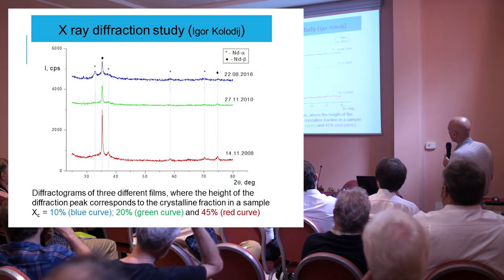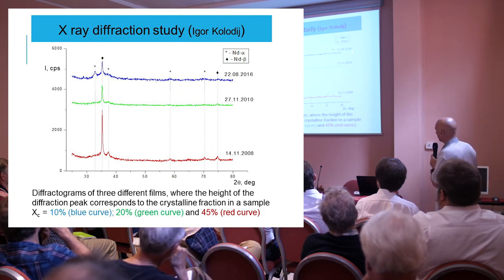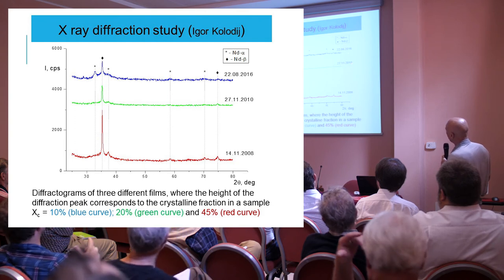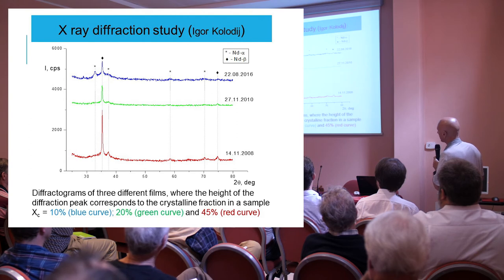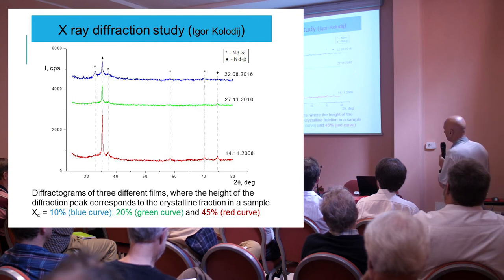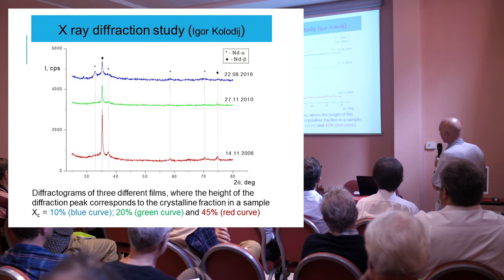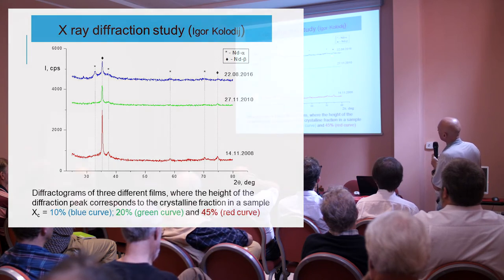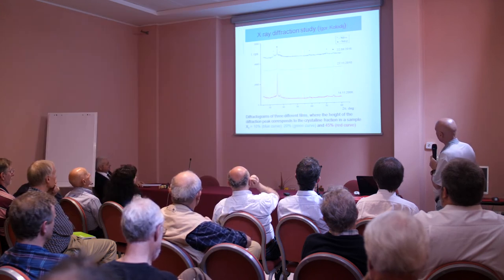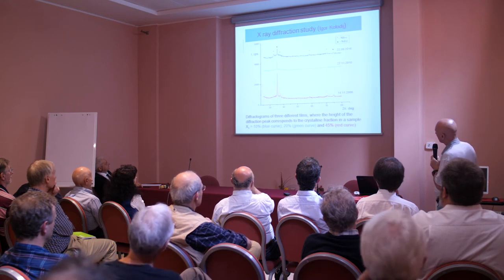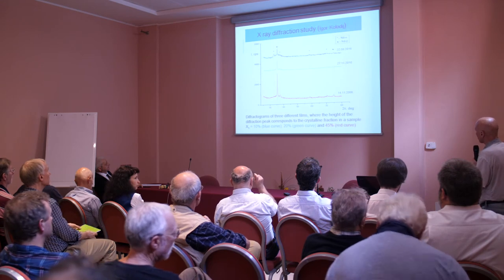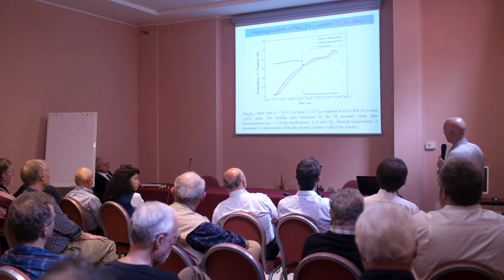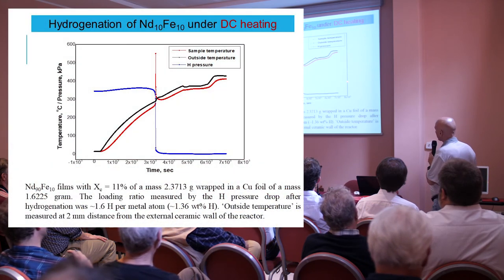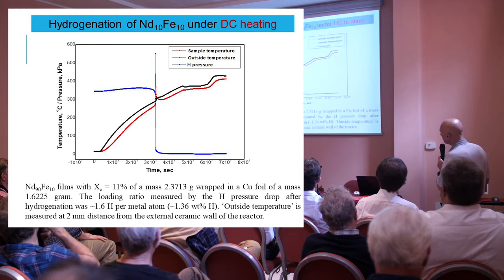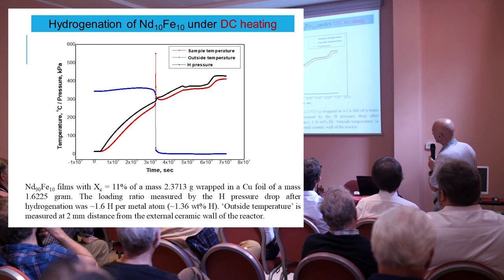And X-ray diffraction study of three types of material produced in different years, starting 8 years ago, 6 years ago, and presently produce different fringes indicating that this one has a more or less half of amorphous structure against the crystalline, and the most fresh one contained approximately 90% of amorphous stage, and intermediate 80%. And these two materials reacted differently to the hydrogen under heating. Here is one example, very characteristic of interaction between the hydrogen. This is the time, this is the temperature.